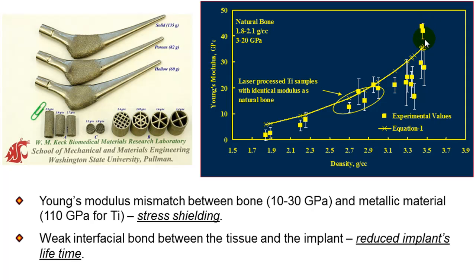Depending on the porosity, if it's more porous, the modulus goes down, and we can easily create structures, even with titanium and pores, that have a modulus similar to natural bone, human bone.